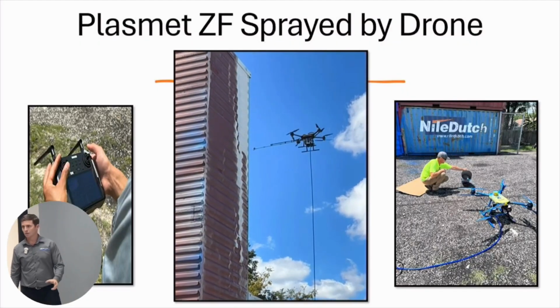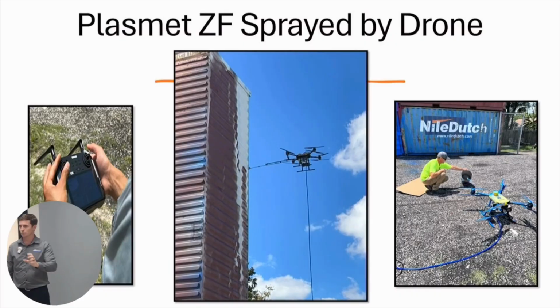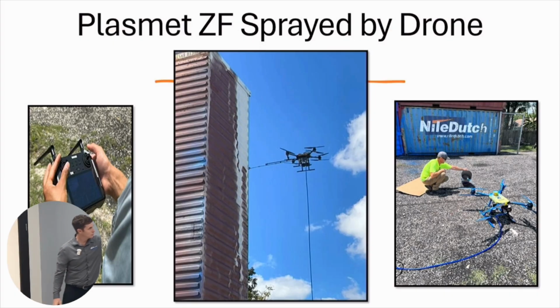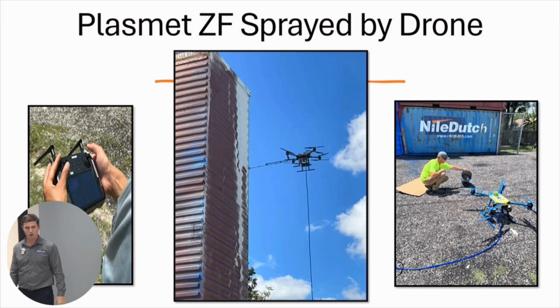On a previous iteration, we had little plates up there so that we could then take down with a high reach and test. We were getting quite the range, but we were getting anywhere from 6 to 12 mils DFT on these plates. And that's going on just multiple passes. As you can see here, you can see the drone, and we're cleaning out the tip. That's just standard practice when you're doing any kind of coating.